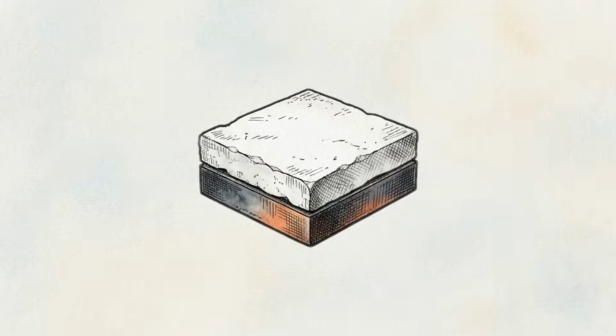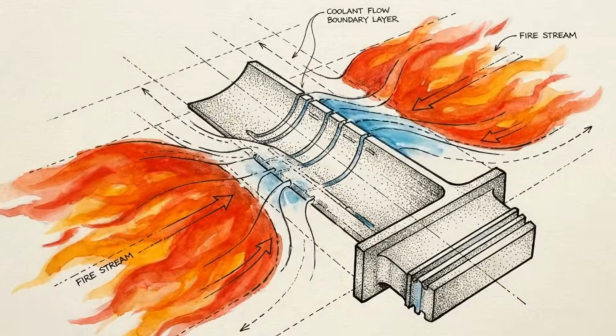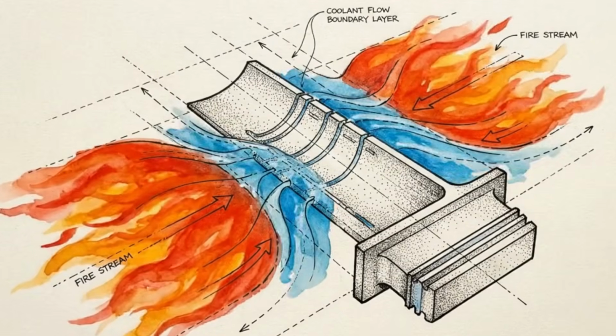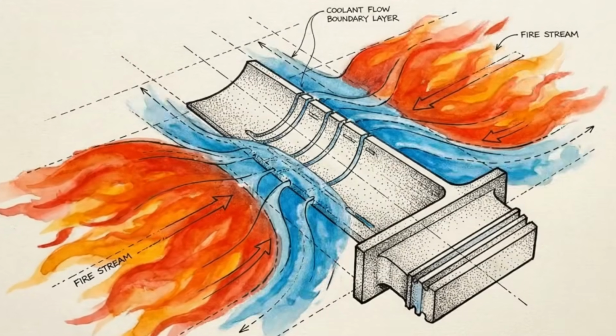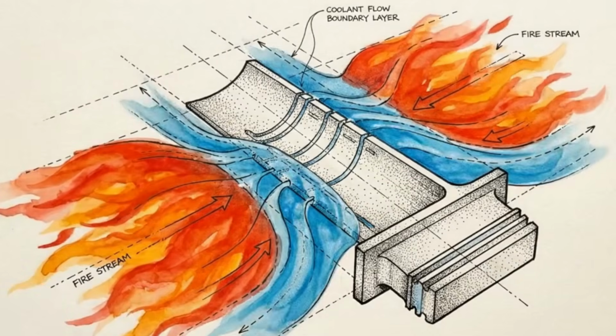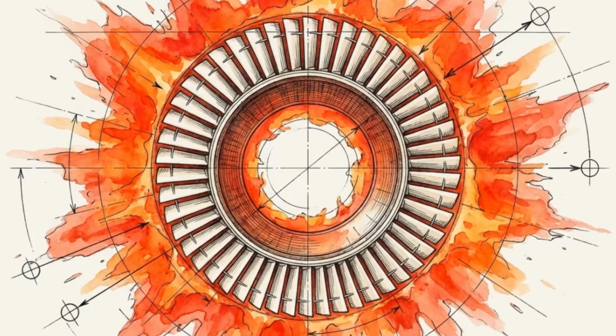This acts as thermal armor, insulating the metal beneath it by up to 170 degrees. This creates a thin, protective envelope of air and ceramic that keeps the metal significantly cooler than the surrounding gas. By sweating cooler air and wearing ceramic armor, the blade survives while submerged in an inferno.